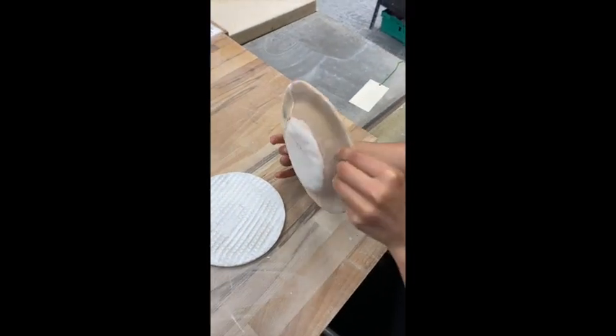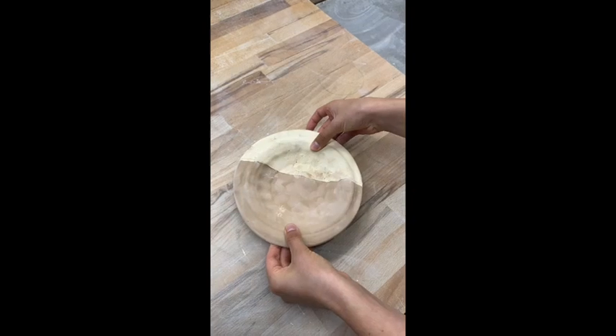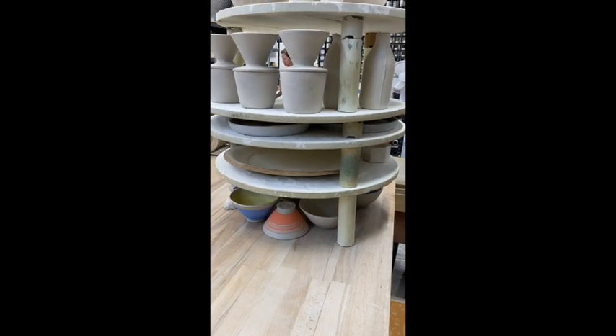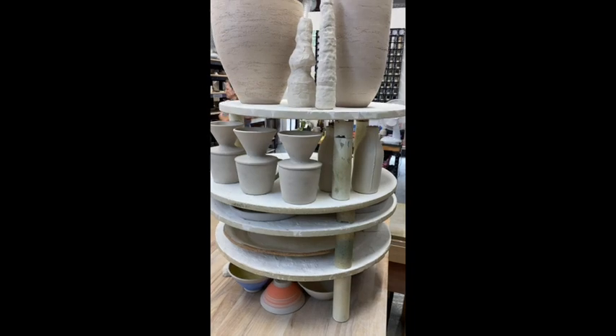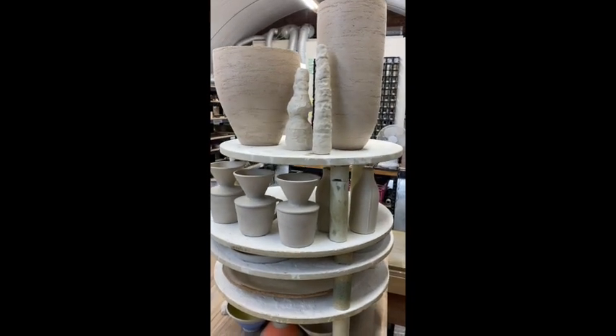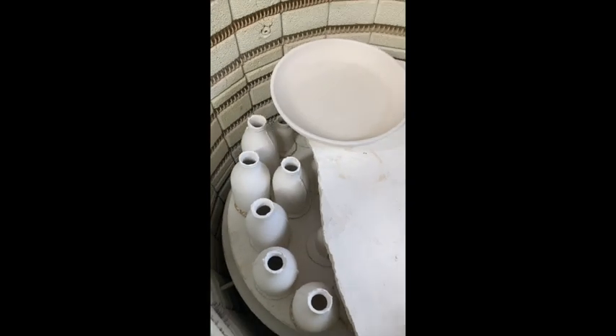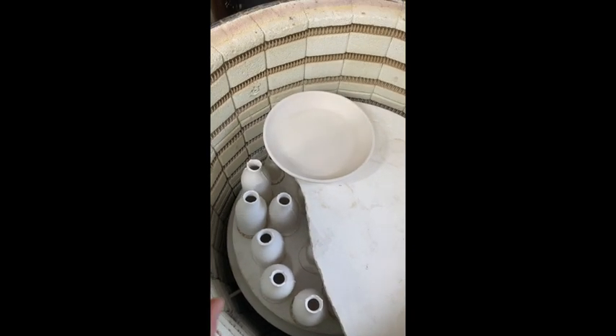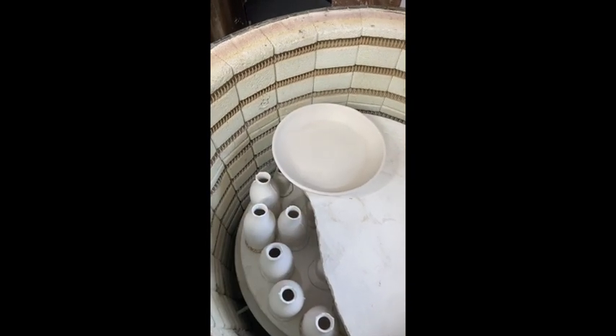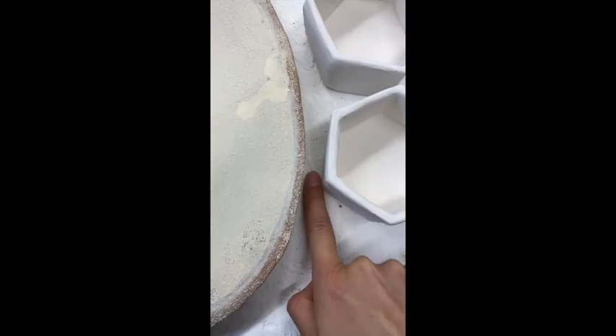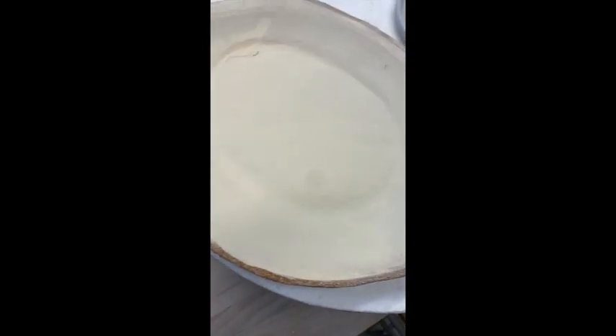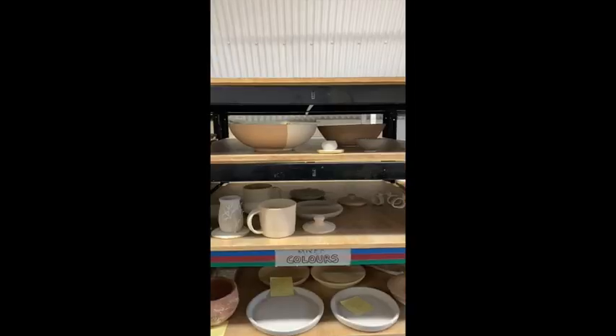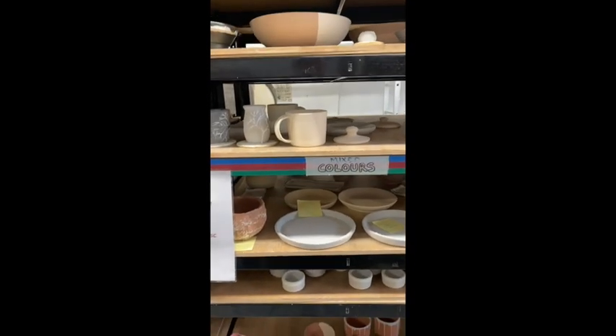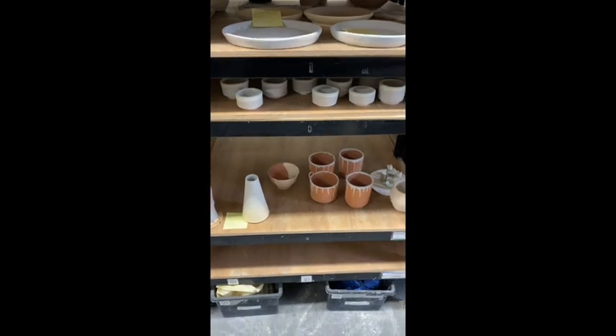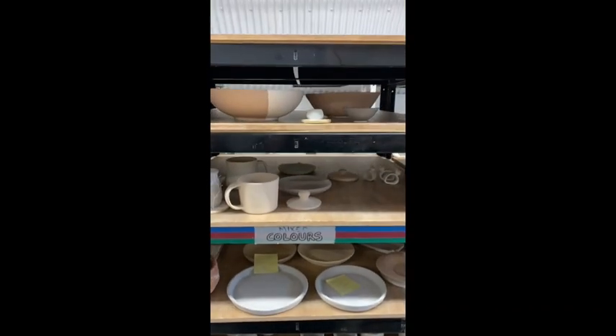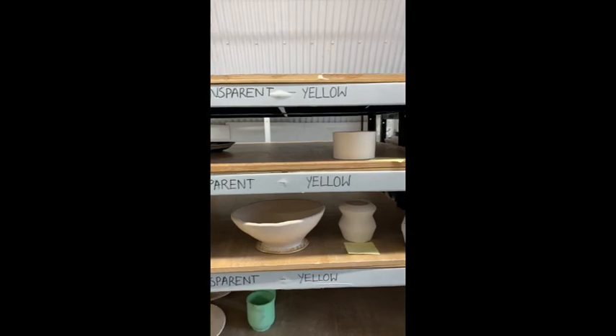the shelf. We like to put plates in the middle of the kiln and larger work at the top of the kiln. Make sure your work isn't overlapping or hanging over the edge of a kiln shelf in case of glazes running. Unlike a bisque pack, glaze work cannot touch in the kiln. There must be at least a finger's width between each piece. In Bellenden Road, we separate dark glazes and white glazes onto different layers. This makes sure there is no flashing in the kiln.